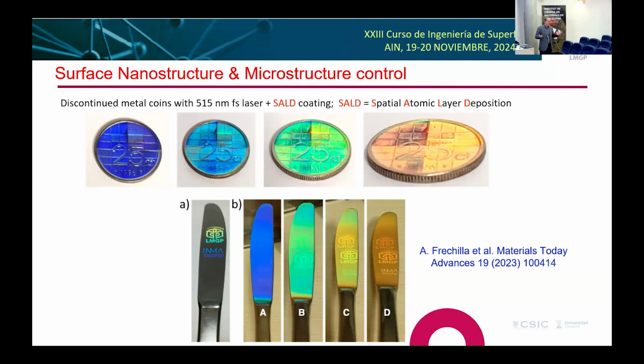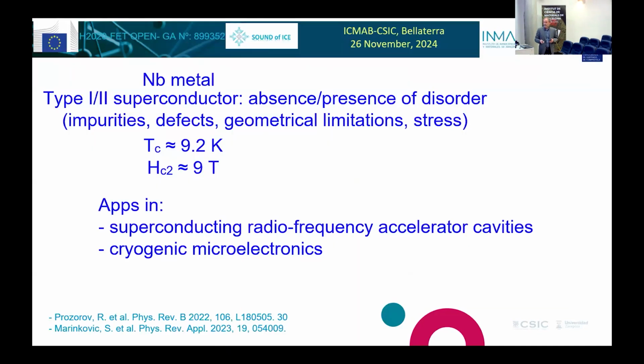So you can do anything with this, and you can also do other things with something which is more electronically functioning. So something which is electromagnetic in nature, like a superconductor. You can take niobium metal. It's a type 2 superconductor with a TC, with a transition at 9.2 Kelvin and a critical field Hc2 of 9 Tesla. And it has applications in superconducting radio frequency accelerator cavities, cryogenic microelectronics, and it's also very interesting from the fundamental point of view.